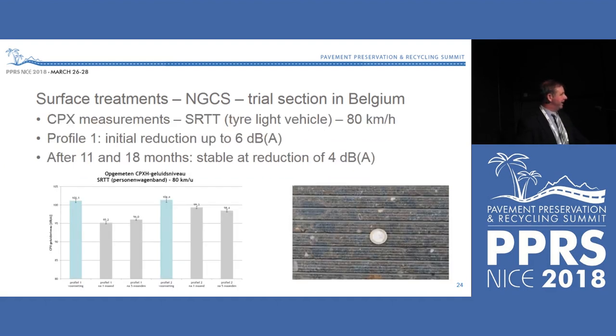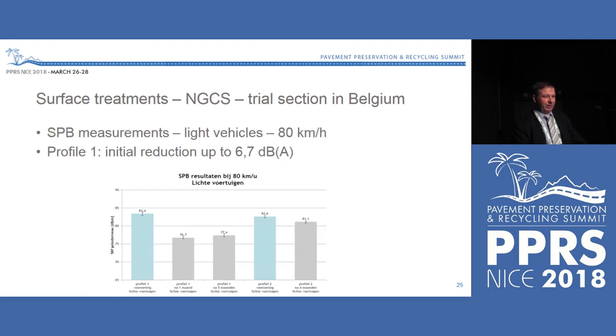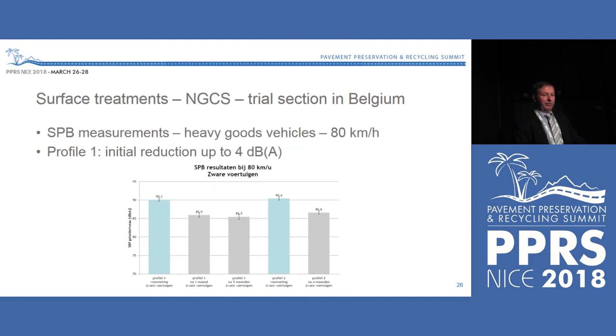So on the right you see the nice picture of this type of finished surface, and you can see that we had a reduction of noise of up to 6 decibels with CPX measurements. There were also later, after 11 and 18 months, the measurements showed an increase and then a stable level of the noise. So it's still a reduction of 4 decibels, which is still spectacular. Also for the statistical pass-by measurements, which is at a point at the side of the road, we saw the same result, initial reduction up to 6.7 dBA. And also for the heavy goods vehicles, there the reduction was somehow lower, up to 4 dBA with statistical pass-by measurements of the traffic noise.